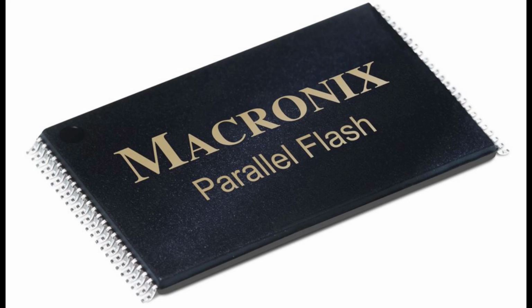The source drain current is sufficiently high to cause some high-energy electrons to jump through the insulating layer onto the FG, via a process called hot electron injection. To erase a NOR flash cell, resetting it to the 1 state, a large voltage of the opposite polarity is applied between the CG and source terminal, pulling the electrons off the FG through Fowler-Nordheim tunneling, FN tunneling. This is known as negative gate source erase.